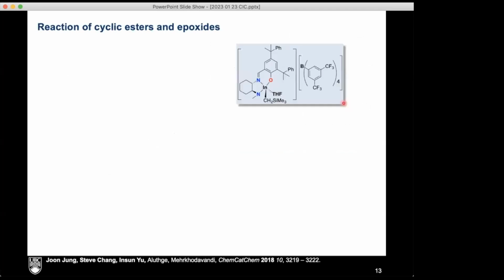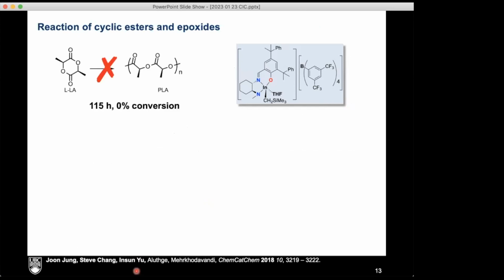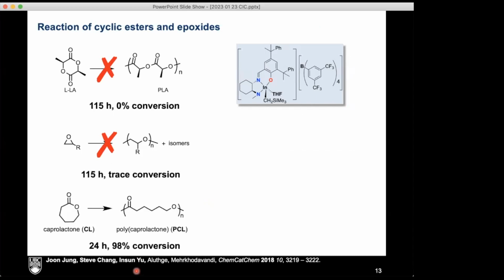Okay, so what do these things do? They were first isolated by former student Insen Yu, and then Jung took over the project. And so we looked at these complexes, and we knew that right away they're not catalysts for lactide polymerization. Immediately they were not polymerizing lactide. They were not polymerizing epoxides. And this is kind of sad because generally epoxides are polymerized by cations, not by these. They do polymerize caprolactone, but extremely slowly. And caprolactone is generally a monomer that is polymerized quite rapidly by all kinds of Lewis acids, but not by these ones. And so this was quite unusual.